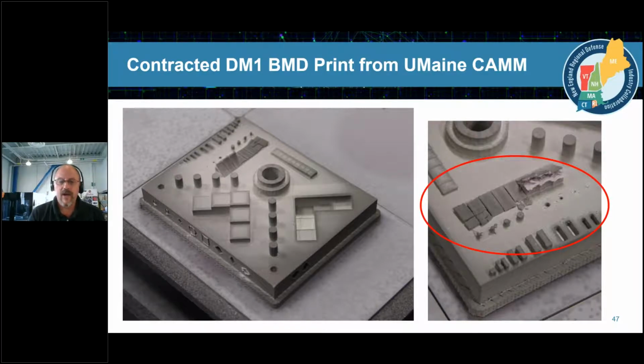As a result, we both encountered some slump, some areas where the part did not uphold overhangs. And we also encountered some print errors, situations where the 3D printer, because it's a fused filament deposition type system, didn't extrude the pink interlayer, which you can kind of see in between these parts here. These are challenges with any type of mechanical system, 3D printers even more so, because these types of parts often take up to a day or more to print. And any error that's introduced into that process can be a failure point.